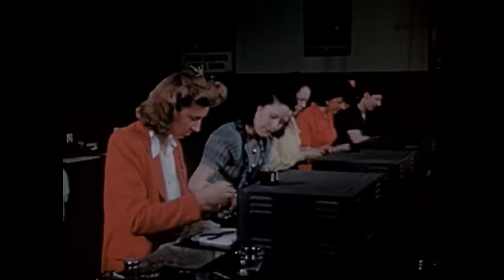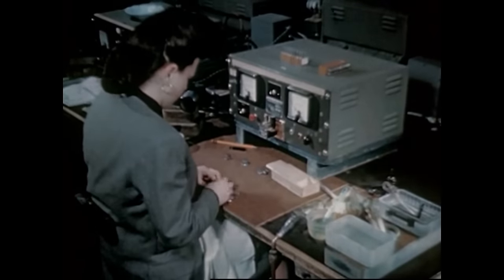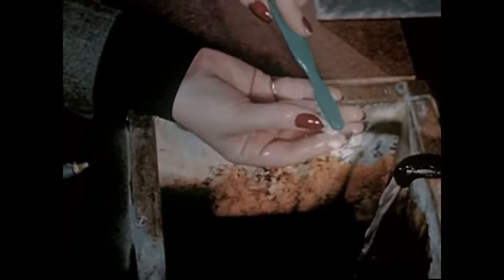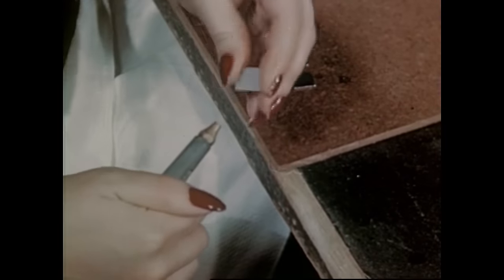Each finishing position is equipped with a small sink, hot running water, compressed air, small dishes containing etching and neutralizing solutions, plastic tongs to hold the crystals, a revolving drum-like edging device, and a comparison oscillator. The crystal is first thoroughly scrubbed with a brush and soap solution. A thoroughly clean surface is necessary if the etching is to take place uniformly. After the scrubbing, it is well rinsed in water. It is thoroughly dried with compressed air